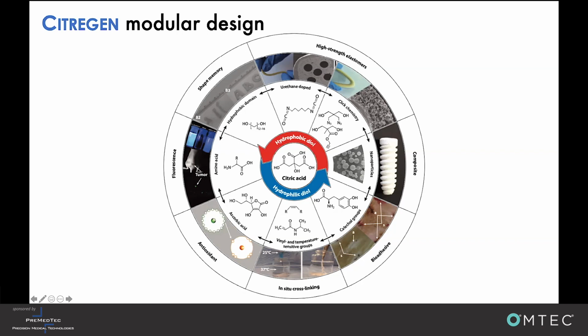We've talked a lot about composites, but you can add molecules with catechol groups and make bioadhesives out of this material. We add vinyl groups to create in situ cross-linking abilities, and ascorbic acid for antioxidant effects. By reacting any of the amino acids to Citregen, you get a very unique fluorescent property. And with hydrophobic domains, larger diols, you get shape memory effects. Then introducing urethane chemistry or click chemistry, we can significantly increase the mechanical properties of Citregen.